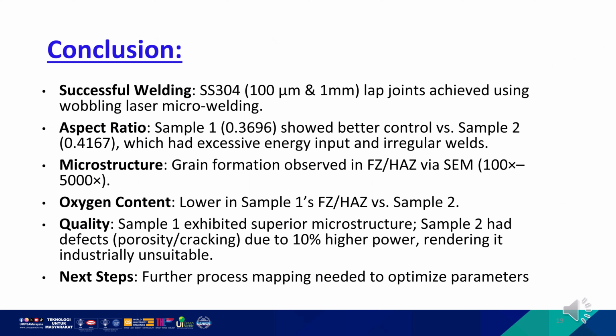So in the conclusion, we successfully laser welded SS304 sheets of 100 micrometer and 1 millimeter using the laser wobbling technique. Sample 1 showed a controlled weld with low defects, while sample 2 had cracks and porosity due to excessive heat, making it more unreliable. In future research, I think further parameter testing should be carried out and optimization is recommended.